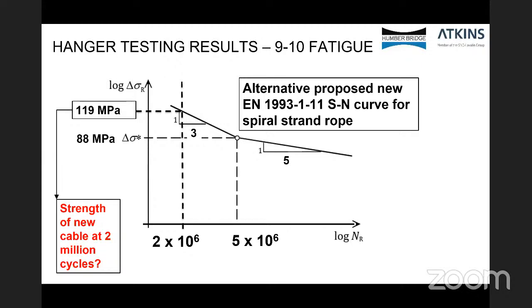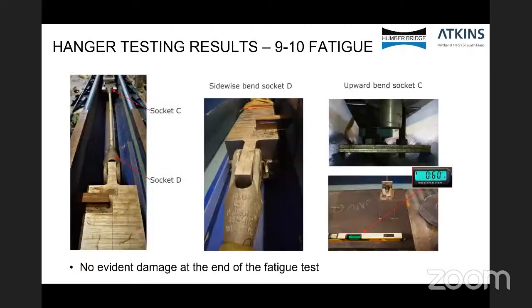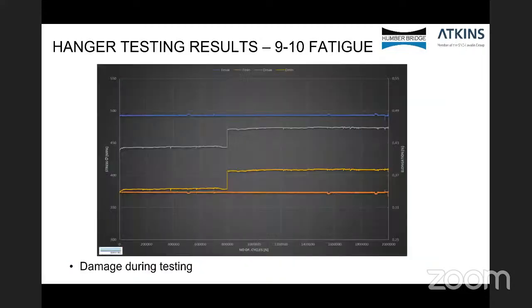Okay, next slide, please. This is just looking at the fatigue results for Hanger 9-10, which was under higher load. Again, there was no evident damage at the end of the fatigue testing. If you look on the next slide, damage during the testing: you can see around the 800,000 cycles, there was a significant jump in load, and we think that was due to 2 wire breakages caused by the fatigue loading. Although no wires could be seen broken on the outer surface, and therefore these wires were broken on the inner surface.